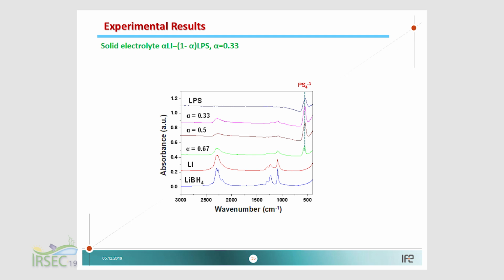We tried to understand what we formed in this specific system. We could see here the addition of lithium borohydride. This is Raman spectroscopy, trying to understand if we really still have BH4 in the system. We could easily recognize the lithium phosphorus sulfide. For the BH4, however, the peak becomes less defined, and we have a decrease in the symmetry. But this is enough to attribute this stretching and bending to BH4, the presence of BH4 in the system.